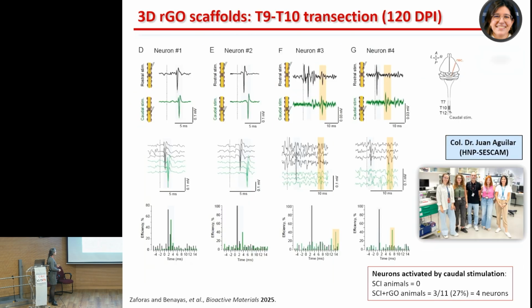And then we used, for the first time, electrophysiology to really see if we could get communication. In our previous model, we couldn't do this because there was an unaffected, or supposedly unaffected, half of the spinal cord that could transfer the signal, right? In this case, no. We removed it completely. So if there is any response in the brain after a caudal stimulation, it has to be because our scaffold is doing something. It's really connecting with the top part. And that's what we did.